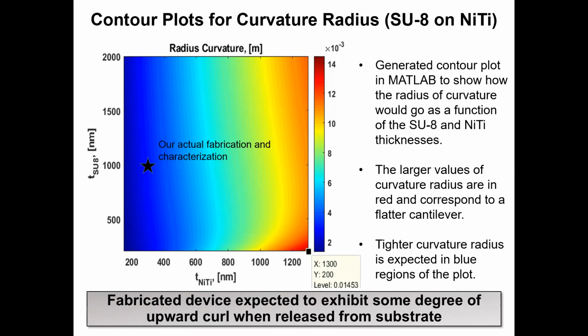So this was an optimization problem in which I had assumed that a flat beam would be most desirable, which ended up being the lower right of this contour map, and that's marked with a box here. Since the contour plot is curvature radius, a higher radius would correspond to a more flat configuration, which happened to correspond to the upper bound on NiTi thickness, which was 1.3 microns in this model, and then the lower bound for SU8 thickness, which was 200 nanometers due to processing limitations on getting SU8 to go any thinner than that.